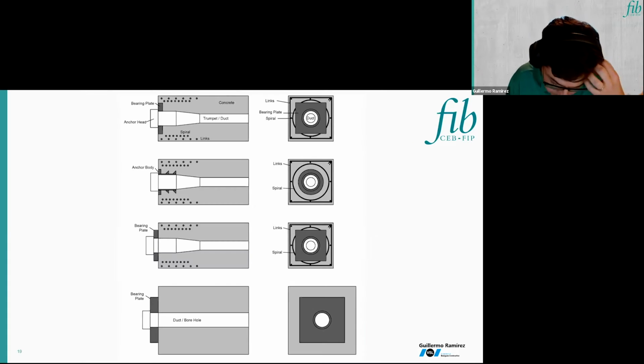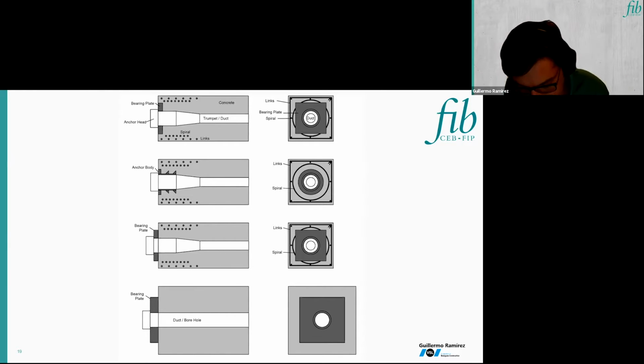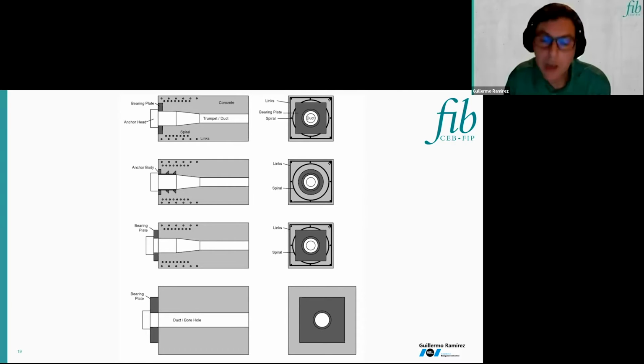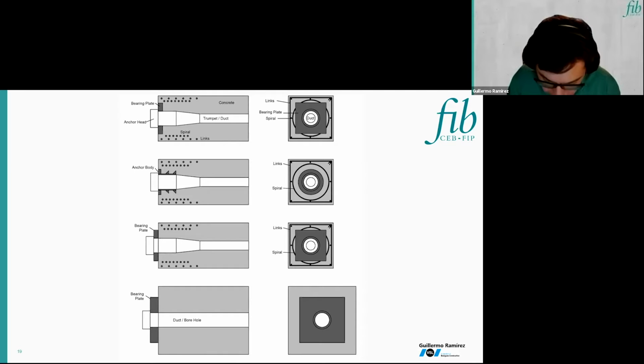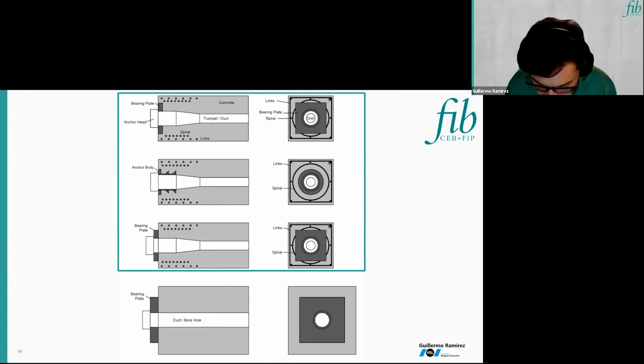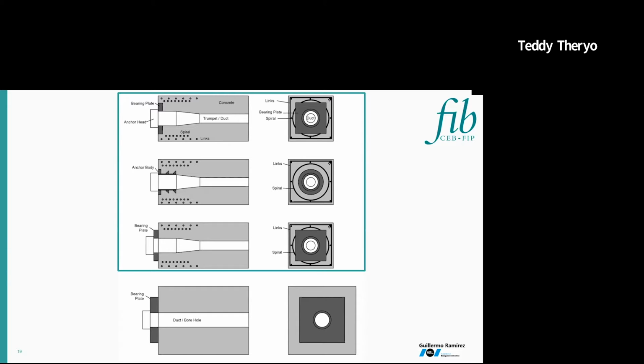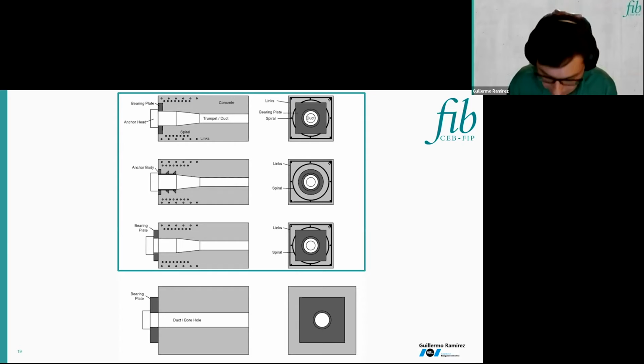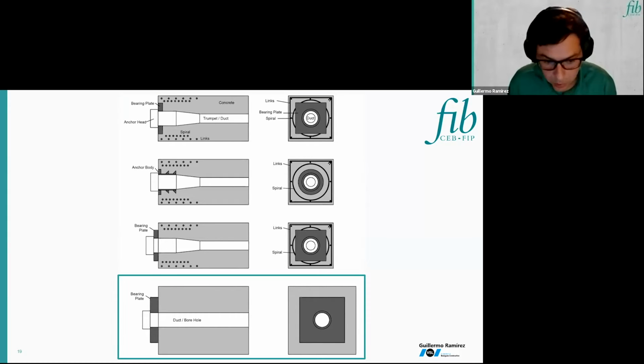If we move now to the anchorages, well, again, at first sight, anchorages for internal and external tendons are not fundamentally different. They can both be composed of anchor heads, bearing plates, anchor bodies, reinforcement steel, but there is one difference that I want to bring your attention to. Anchor bodies or bearing plates can be cast in structural concrete in combination with confinement reinforcement only for new bridges or strengthening measures which include the addition of new concrete elements. Some strengthening measures, though, require direct load transfer to old concrete. In these cases, additional confinement and bursting reinforcement cannot be installed. And then usually larger, specifically designed bearing plates are required.